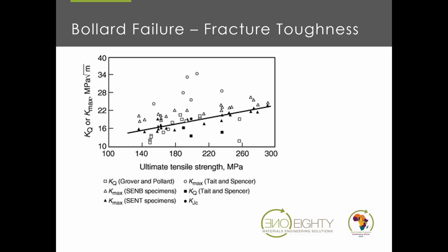They won't kill you. And as you can see here, this is a graph for cast iron, and it typically shows you the sort of fracture toughness you can expect for cast irons with an ultimate tensile strength of between 140 and 260 MPa. This is a fairly modern graph. The bollard was installed in 1961. So not necessarily relevant to the bollard that actually failed, but this is the sort of fracture toughness properties you would expect today of cast irons based on their UTS. We're clearly dealing with something that is outside of this range.